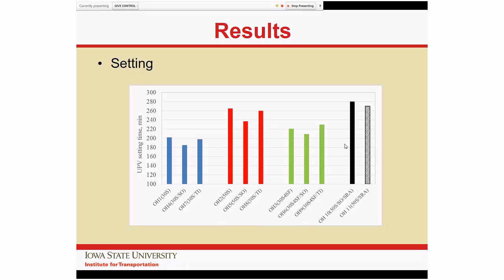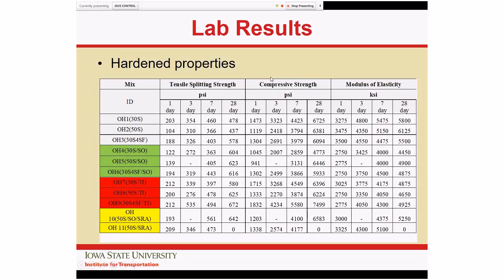All right, so for the setting time, where there is a fairly big signal is the 30% slag, which typically set at 3 hours. The 50% systems were quite a lot slower. The silica fume brought it back down a little, and the SRAs also slowed things down fairly significantly. But in a way, there's no right or wrong answer on this. It just needs to be communicated to the contractor that things are going to be slowed down. The way they do finishing and curing has to be adjusted a little bit, in that we don't want to put curing compound on too early. We also don't want to be doing final finishing too early if the system hasn't set yet.